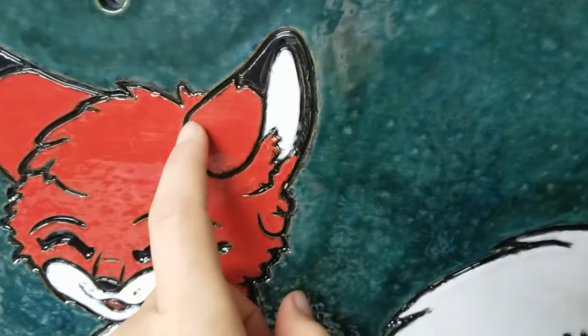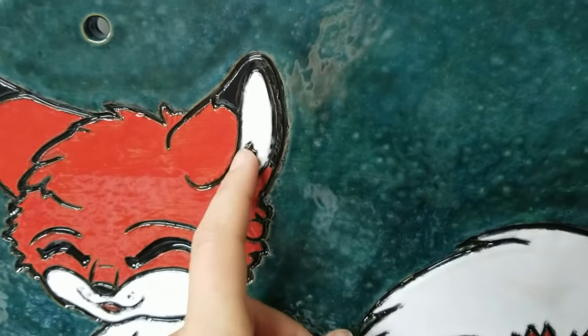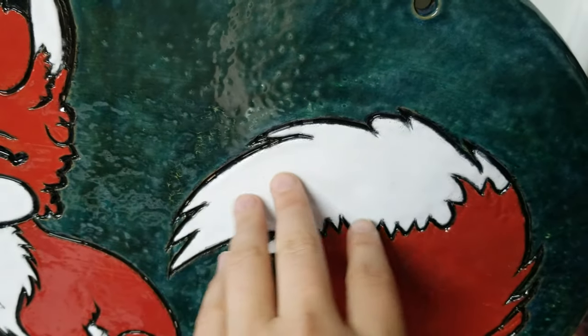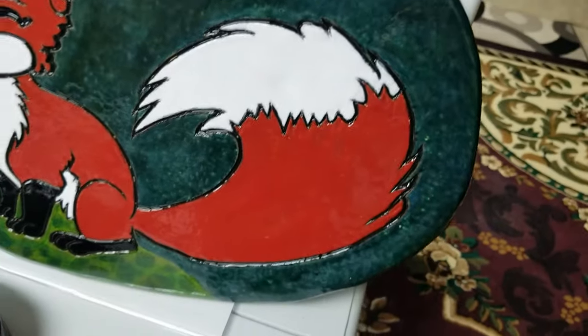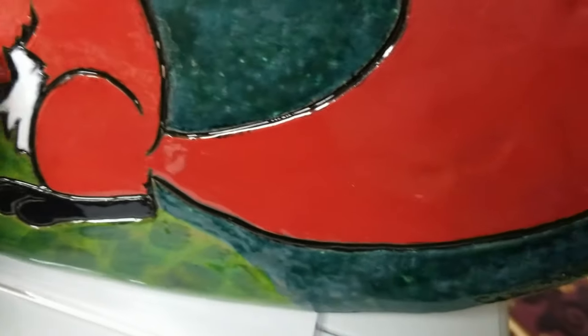These are actually indentations, which is the only reason these glazes actually stayed where they were put, is because this black likes to sink. Just watch the whites in our kiln, because if you put more than like 2 coats on, they like to bubble. So you have to really, really watch. There's a little bit of bubbling. Where was it?